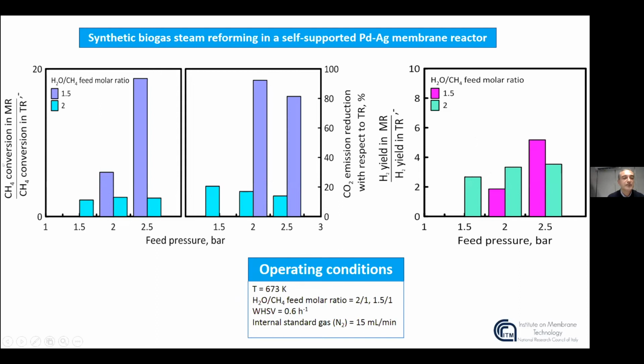the membrane reactor is always the best choice with respect to a conventional reformer, and in particular, under a defect of steam, where the increase of pressure determines a great advantage of the membrane reactor with respect to the traditional reactor, both for conversion and CO2 emission reduction. But also in terms of hydrogen yield, the membrane reactor results to be a better choice than a traditional reactor by increasing the feed pressure.